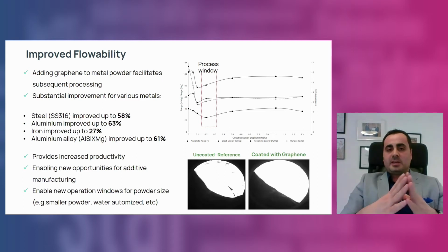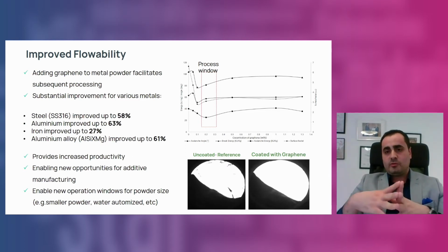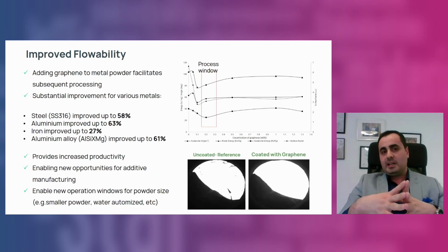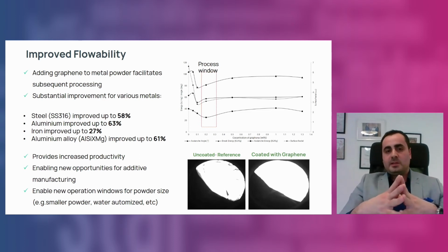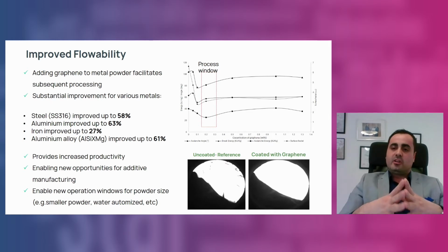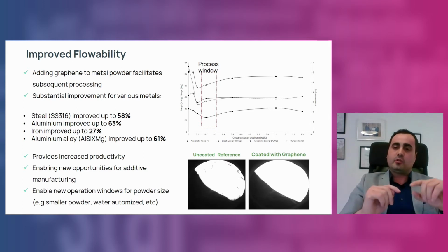And here you can see some examples. For example, in steel, the improvement was 58%. In aluminum, it was 63%. In iron, pure iron without alloying elements, it was 27%. And in aluminum alloy, it was 61%. So these numbers are really great. And if they can combine with the effect of graphene later on at the component level, they are even greater.